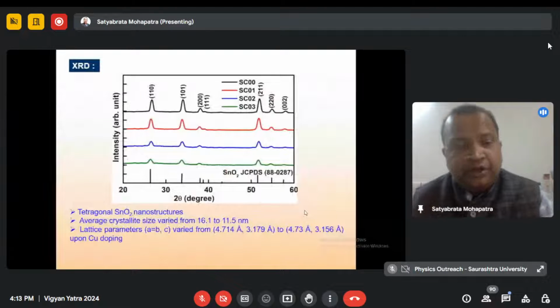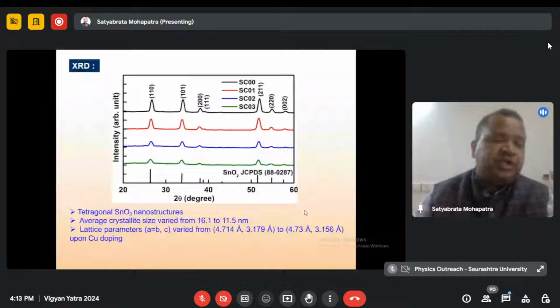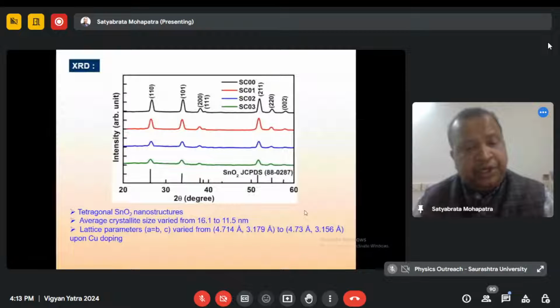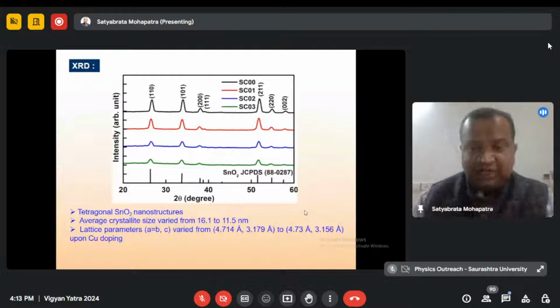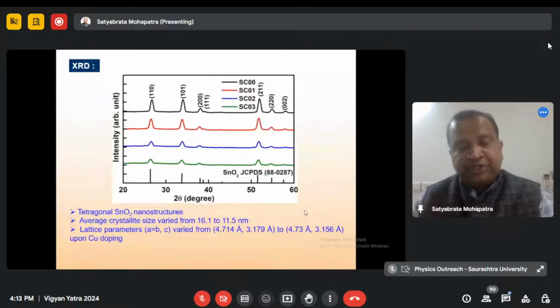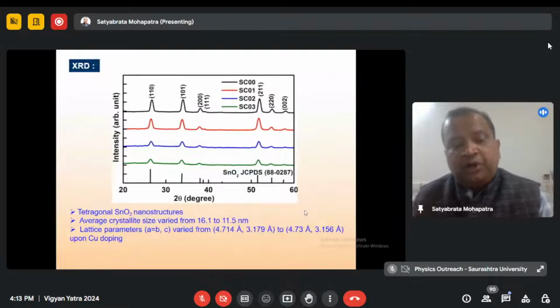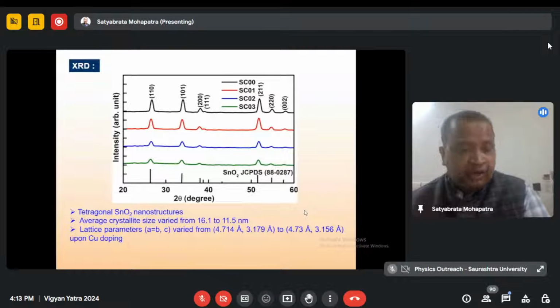The XRD patterns confirm again the tetragonal tin oxide structure of these nanosheets, and the average crystallite size reduced from 16.1 to 11.5 nanometer upon copper doping. So there is a slight decrease in the crystallite size, and the lattice parameters varied from 4.714 angstrom and 3.179 angstrom to 4.73 and 3.156 angstrom upon copper doping. So there you see that there are changes in the lattice strain, and of course a decrease in the crystallite size on copper doping.